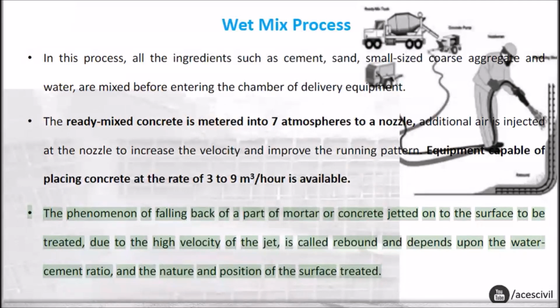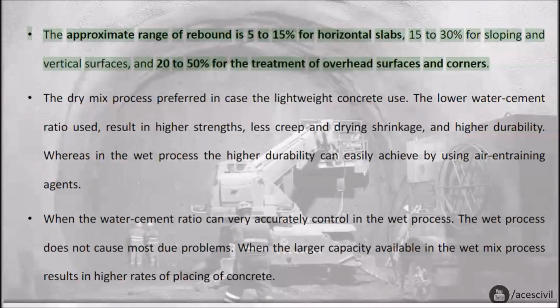The phenomenon of falling back of a part of the mortar or concrete jetted onto the surface to be treated, due to the high velocity of the jet, is called rebound and depends upon the water-cement ratio, and the nature and position of the surface treated. The approximate range of rebound is 5 to 15% for horizontal slabs, 15 to 30% for sloping and vertical surfaces, and 20 to 50% for the treatment of overhead surfaces and corners.